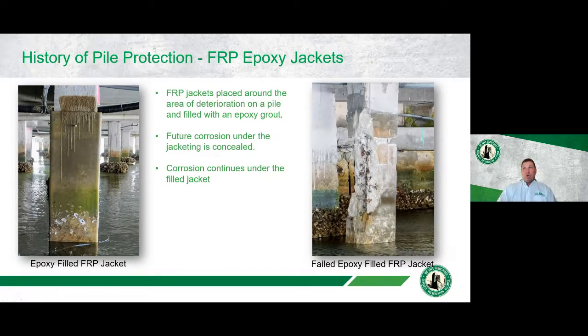And one thing to note is that even though this jacket has been put around it, it's going to reduce the oxygen somewhat and some of the moisture levels, corrosion can still continue underneath. And you can see how the corrosion kept growing and growing and growing. And you can actually see that all of the reinforcement within this pile is basically completely gone. And now when we were looking at this pile with the jacket on it, you couldn't see any of this distress. So during the installation of a new cathodic protection system, a new cathodic protection jacket, it was just decided that they were going to remove these jackets so that they could visually inspect it.